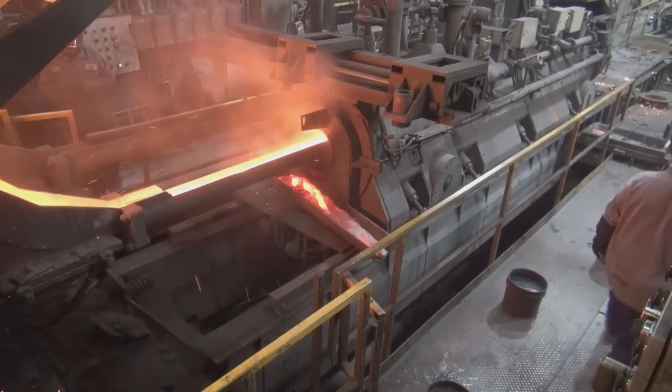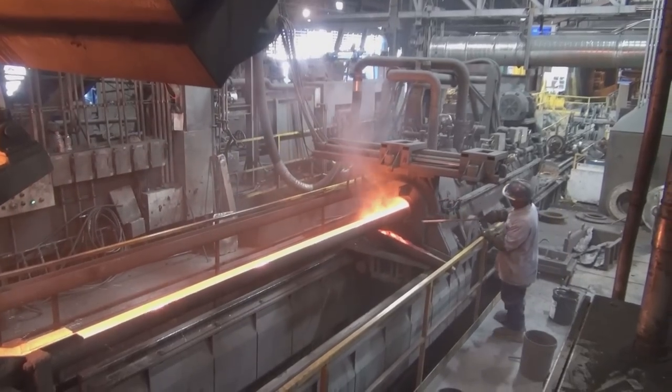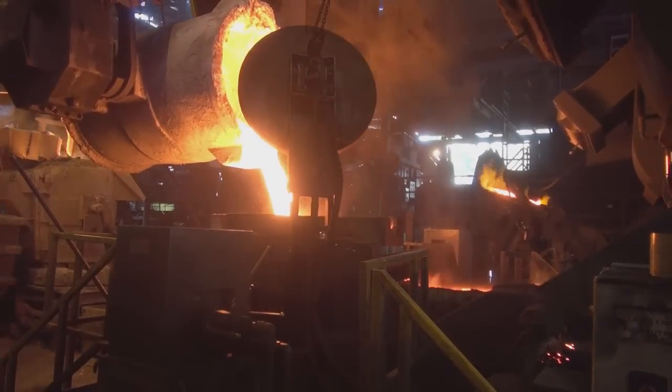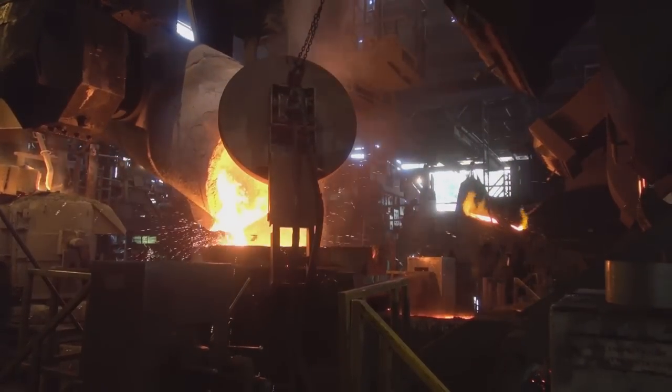Ductile pipe is manufactured using the de Lavaud process, which consists of pouring molten iron of appropriate composition into a spinning horizontal cylindrical steel mold. Each casting machine is equipped with a pouring ladle. These smaller ladles hold enough molten iron to make several pieces of pipe before needing to be refilled.